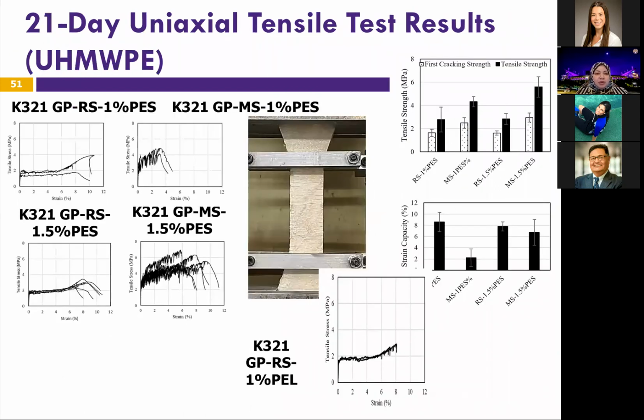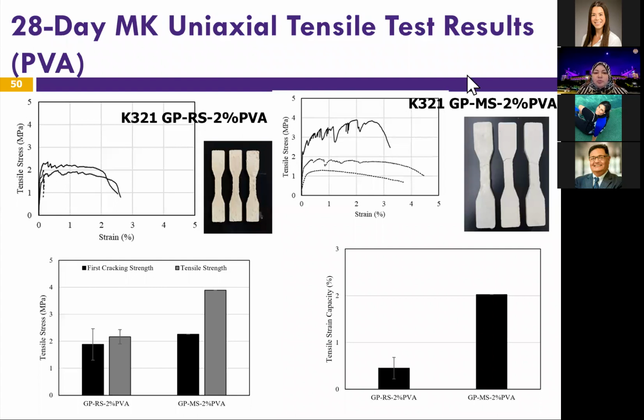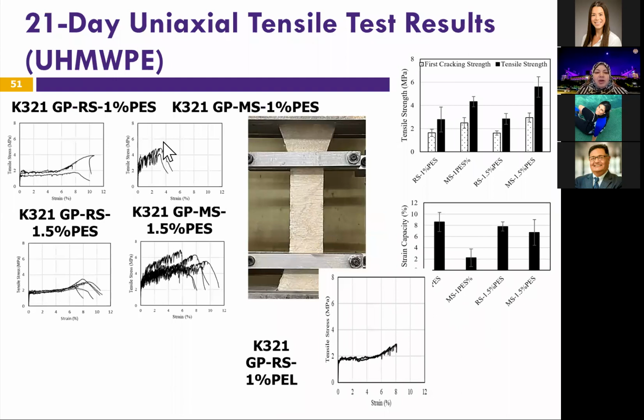This is the part that I was telling you about that's very interesting. So the polyethylene fibers that Svetlana is developing are actually working quite well. Let me go back here. And if you notice here, it's 2%. So the volume fraction here is 2% of the fibers. But we are only using 1% with the polyethylene. We are getting very encouraging results at a much lower volume fraction, which will reduce the cost drastically. And we are experimenting with both long fibers and short fibers, because the more that we can use existing fibers or low cost fibers, the more the cost of the ECCs will come down. So I'm very excited about this.